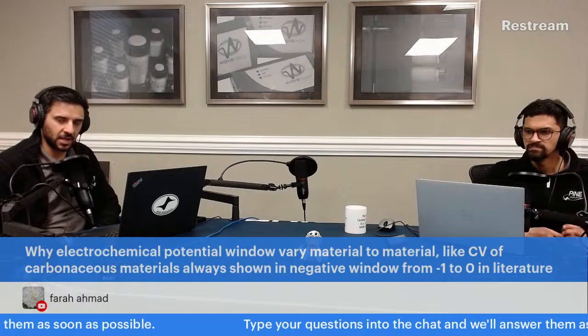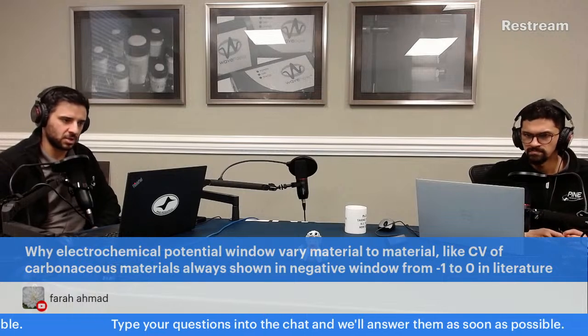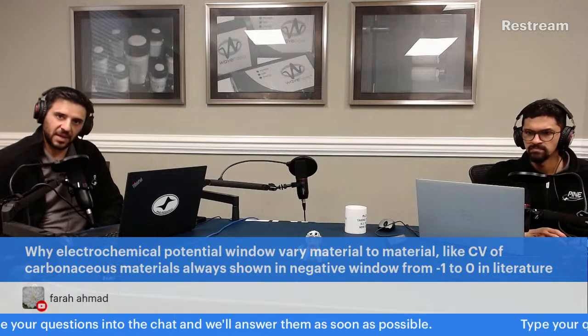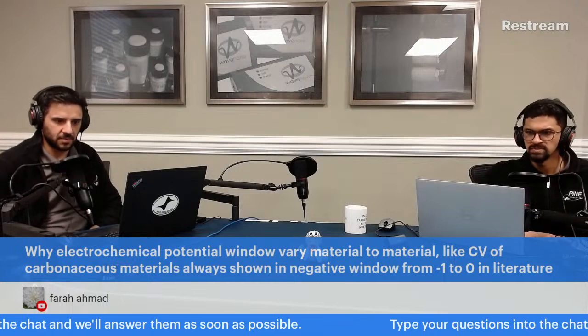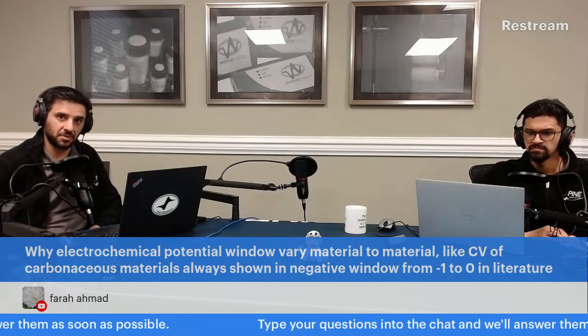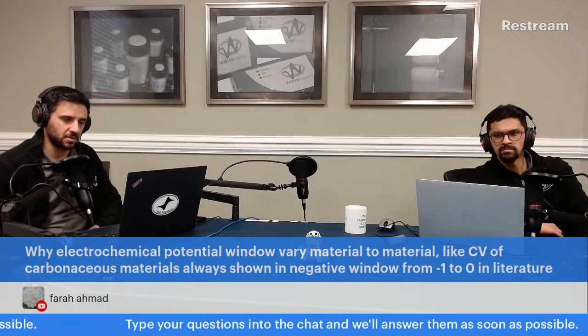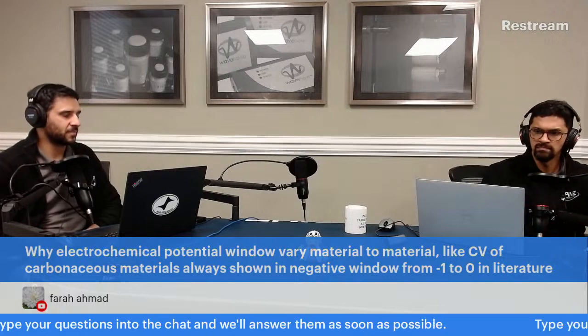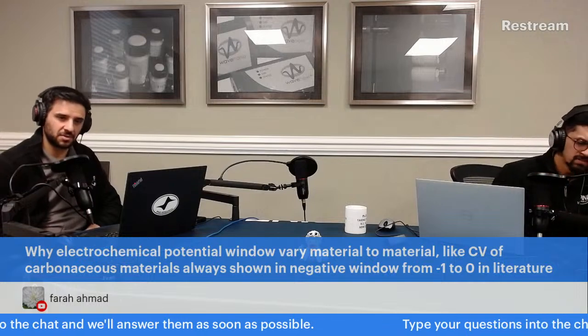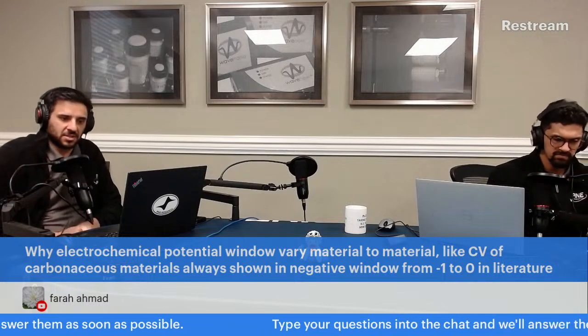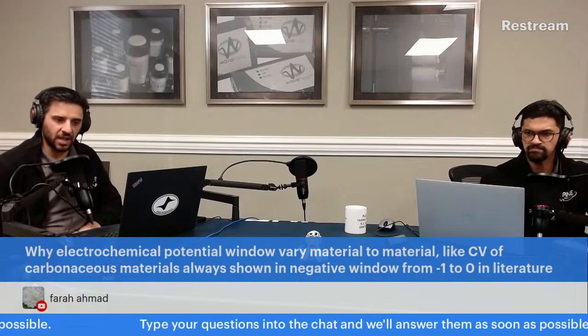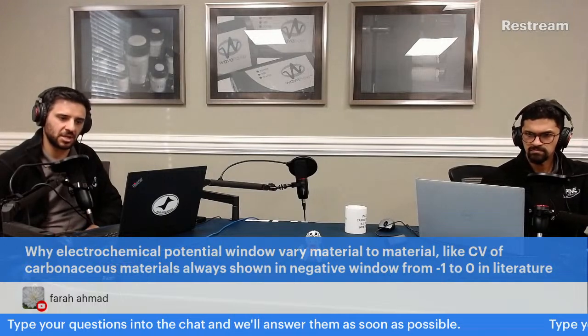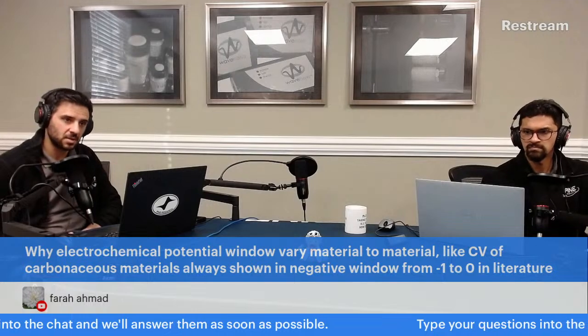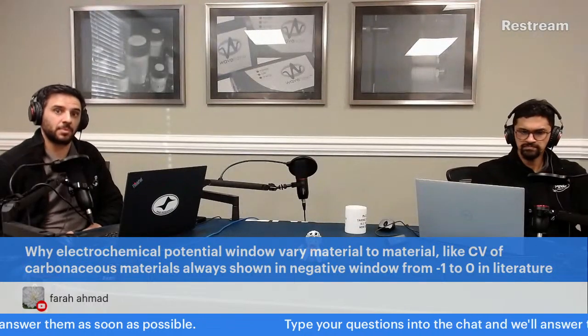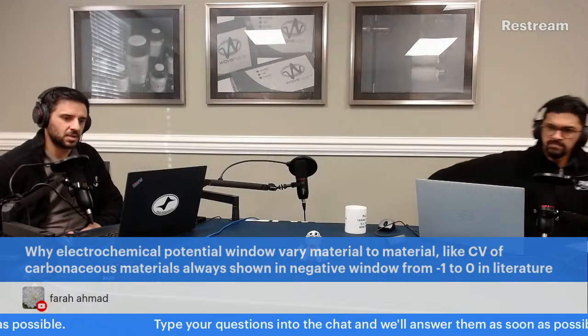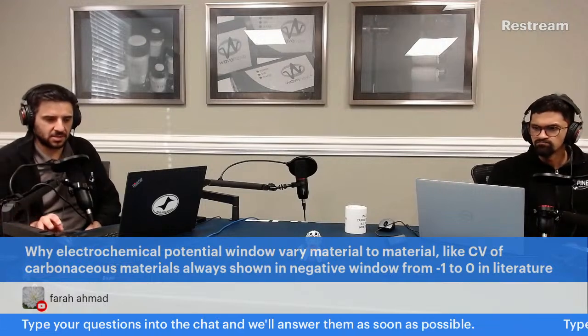And then some electrodes, you have to limit their window or change their window because the electrode itself might be damaged. For example, with carbonaceous materials, generally speaking, you don't want to overly oxidize them. They could damage the electrode itself. But negative potentials aren't as dangerous generally on the carbon. So that might be an example of why you're seeing more negative potentials on some carbonaceous materials as opposed to more positive ones, because you might just oxidize the carbon itself and then you fry your electrode.